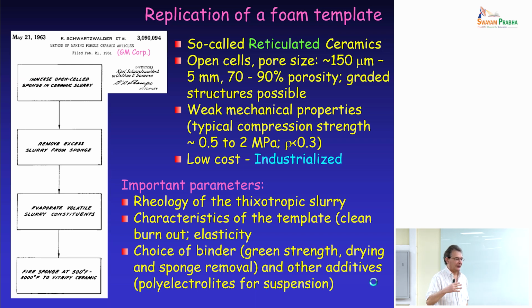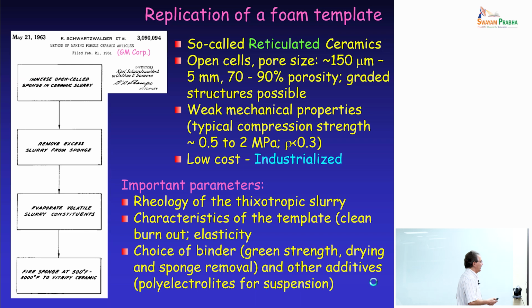Of course, you need to tailor the adhesion of the slurry to the polymeric template. The polymeric template needs to be flexible and compressible because, once you dip it and extract it from the slurry, the slurry not only coats the edges of the polymeric foam, but it also fills, at least in part, the void. So you need to squeeze the foam to push out the unwanted trapped slurry. And then you need to fire to obtain your ceramic material. And there are a lot of parameters that you can work with in order to optimize the properties of the material when you make it.